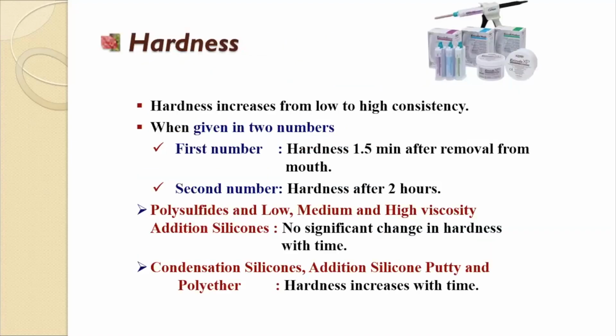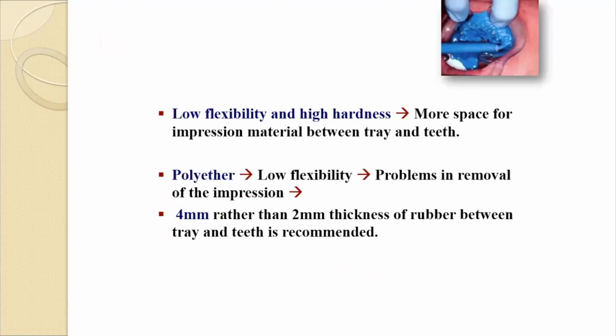And coming to your hardness, for your polysulfides and low, medium and high viscosity addition silicones, there is no significant change in hardness with time. And for condensation silicones, addition silicone putty and polyether, hardness increases with time. So low flexibility and high hardness. So if there is more space for the impression material between the tray and teeth, with polyether, low flexibility, there are problems in removal of the impression. So 4 mm rather than 2 mm thickness of the rubber between the tray and the teeth is recommended. So at least 4 mm of the material should be present between your tray and your impression surface. So this would help.